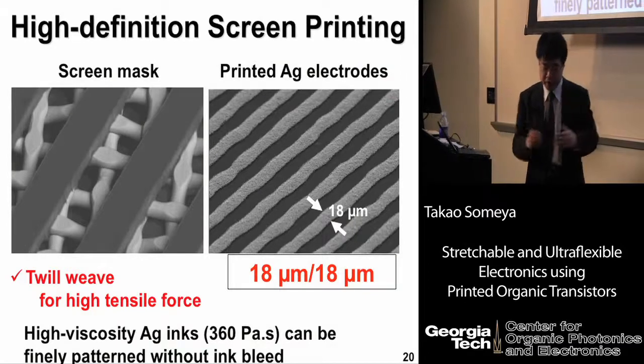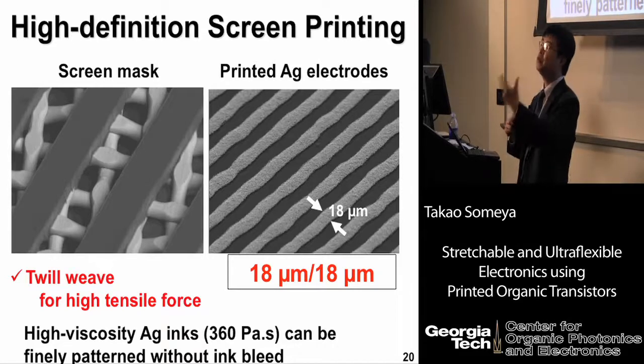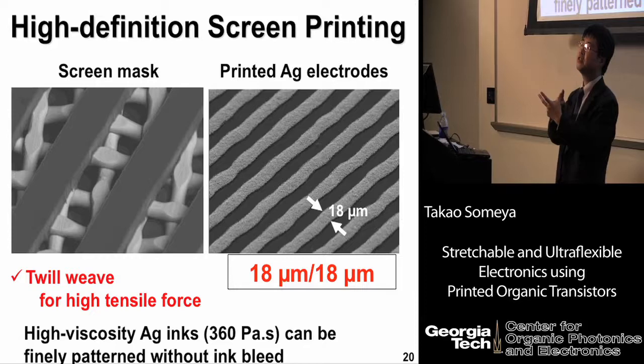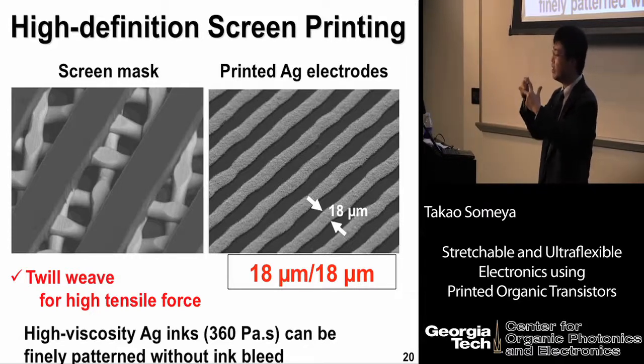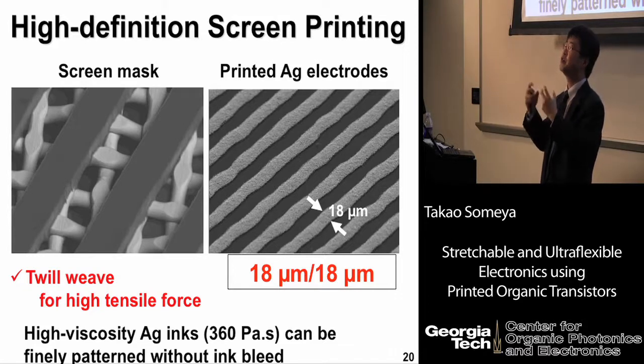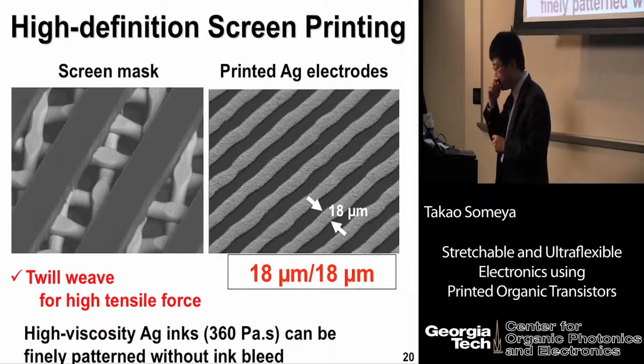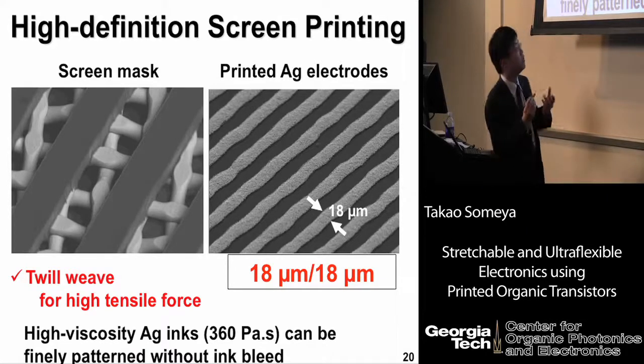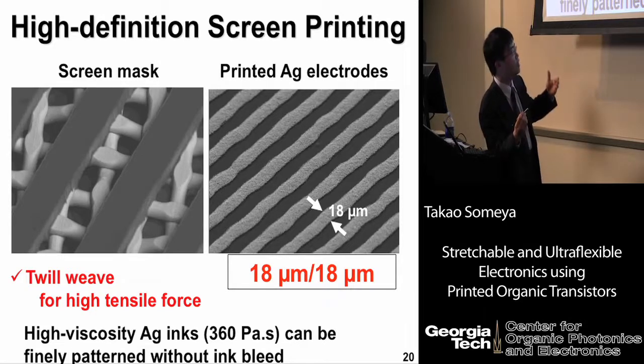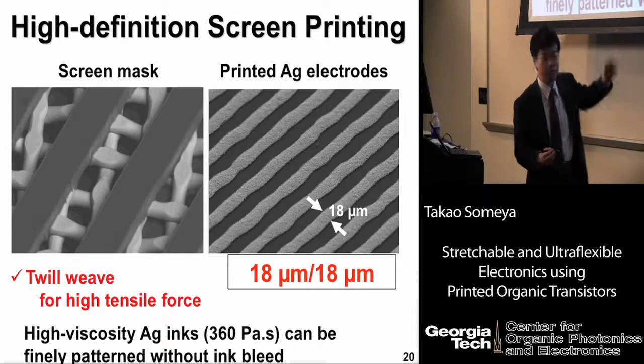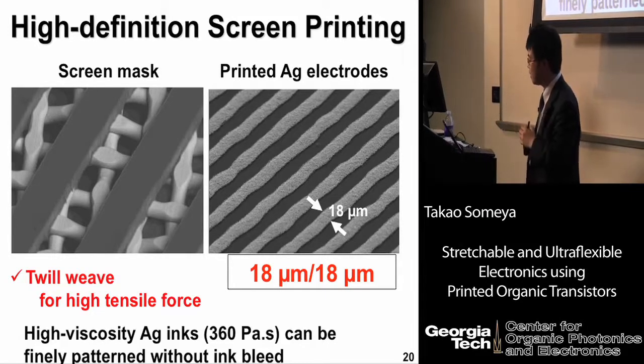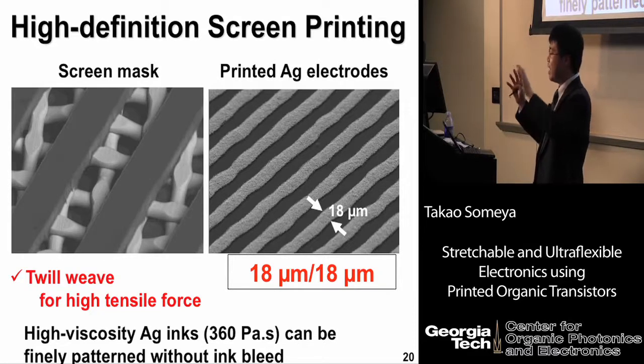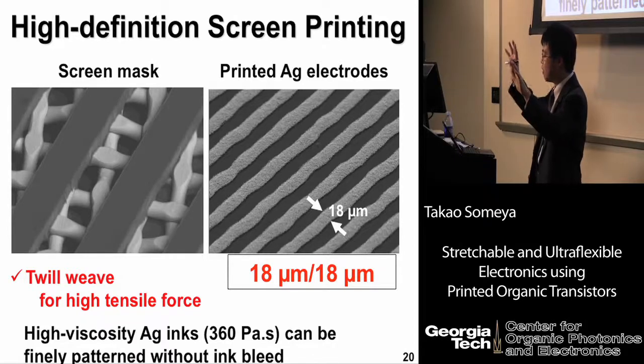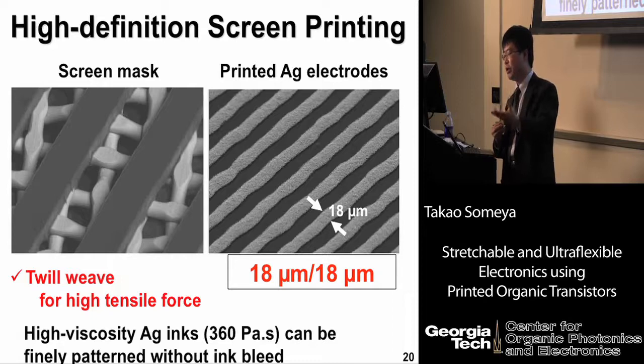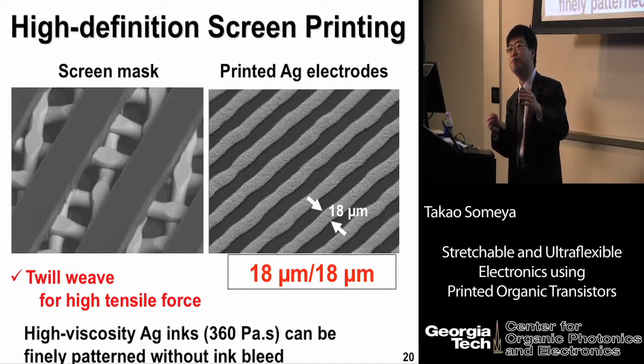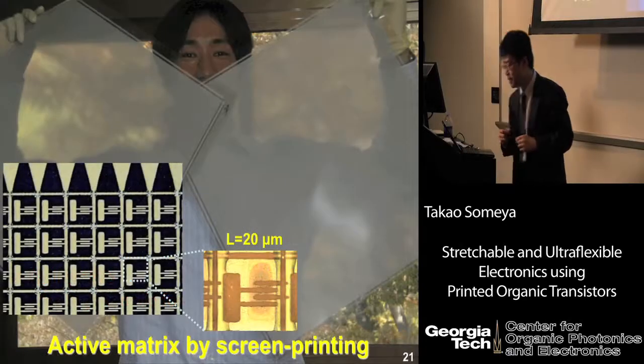In order to improve the spatial resolution of screen printing, we have to optimize 3 kinds of things. One is the screen mask, and another is optimization of viscosity of the ink. And also, we have to play around with the printing process parameters. But anyway, if I use the twill weave stainless steel mask to improve the tensile force, now we can apply really high viscosity ink, something like 360 pascal second. So by combining the high tensile strain mask and also high viscosity ink, we can reproducibly print 18 micron fine patterns by screen printing.